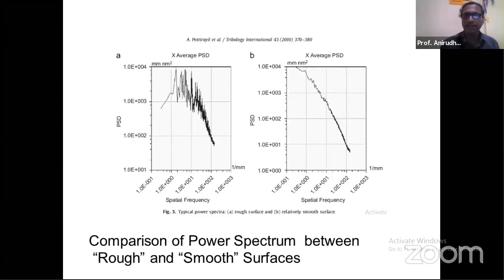So we thought, if you just look at the power spectrum from these surfaces, then I have shown two different power spectra, one which belongs to a so-called rough surface, and I have shown the power spectrum of another surface which was classified as smooth, as we saw in the beginning on some 3-4 slides previous to this. We saw a rough surface, we saw a smooth surface. So obviously we would expect friction to be high for the rough one and friction to be low for the smoother one. Now when we observe the power spectra from those surfaces, we found something which is very striking.